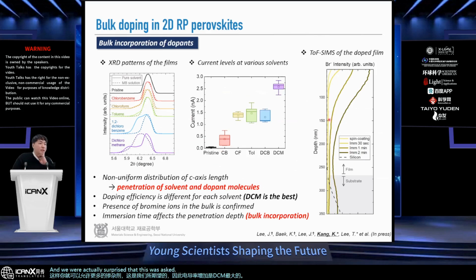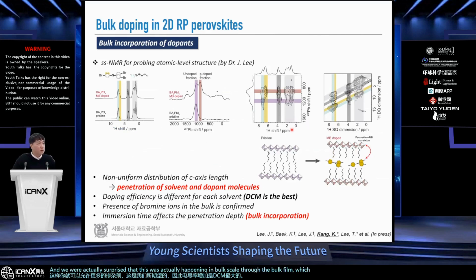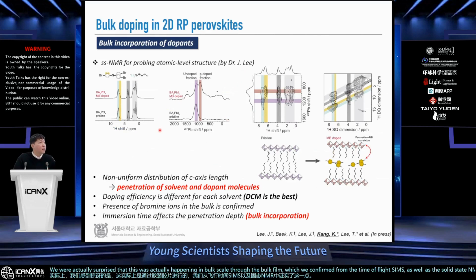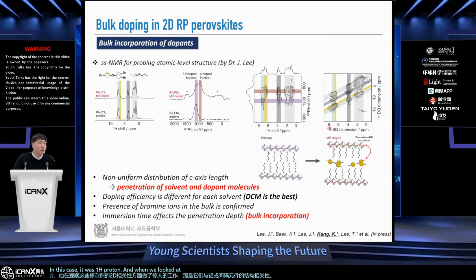And we were actually surprised that this was happening at bulk scale through the bulk film, which we confirmed from time of flight SIMS, as well as solid state NMR, with JJ, who did amazing work on 2D correlation, looking at these dopants as well as their structural correlation with either the lead or the spacer elements. In this case, it was 1H proton. And when we looked at the correlation between 1H of these and also 1H on the dopants, they seem to be highly correlated, which meant that these molecules were lying in the proximity of the spacers.